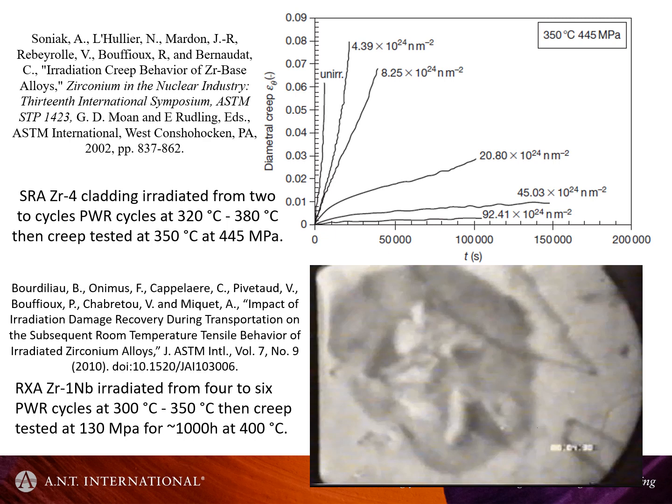But when you look at the doses here, they're very high doses. These doses are more than an order of magnitude larger than the type of doses I've been talking about earlier, where we get saturation in the A-type damage. So a lot of this hardening we see here, the reduction in the out-reactor thermal creep rate, has to be because of some other feature. Either that or the doses are wrong. I just don't understand it.